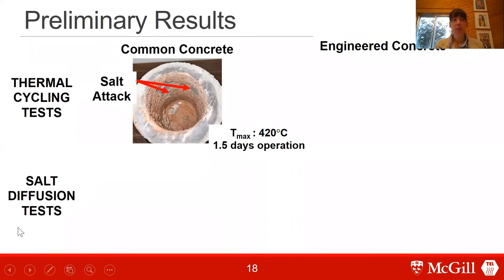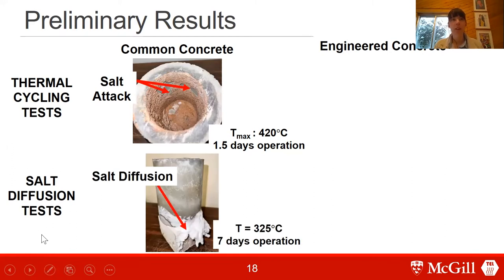And we also have some salt diffusion issues. So concrete is naturally a little porous, and so it allows liquids to diffuse through the walls. So over 7 days of operation, you could see the salt diffusing through the walls and actually pouring through the sides of the walls because of salt diffusion.